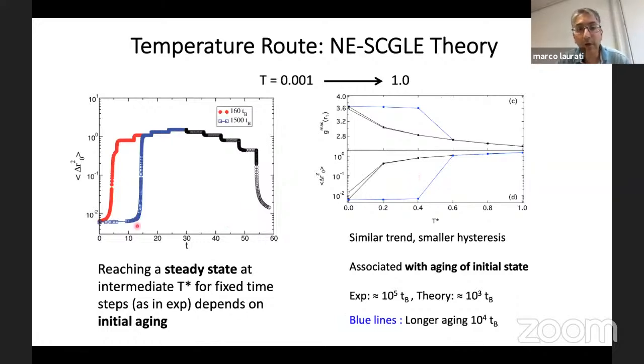And in the theory, we could see that this essentially depends on the fact that when you do a protocol in which you change the temperature in steps at fixed time, what happens is that if the system is longer aged, there are some intermediate steps in which the system is not able to reach the steady state. So that's why you get this hysteresis in the system.